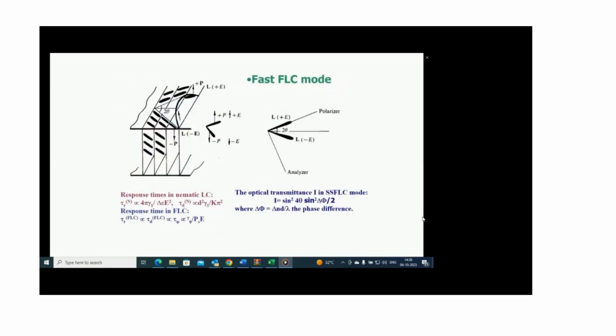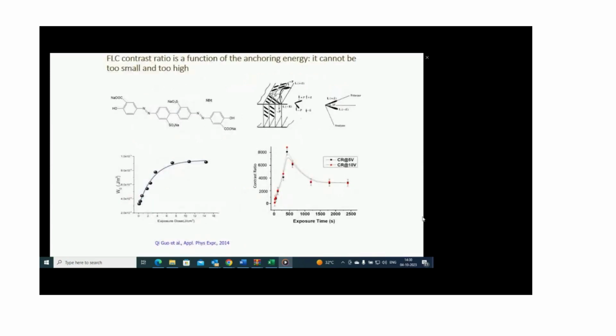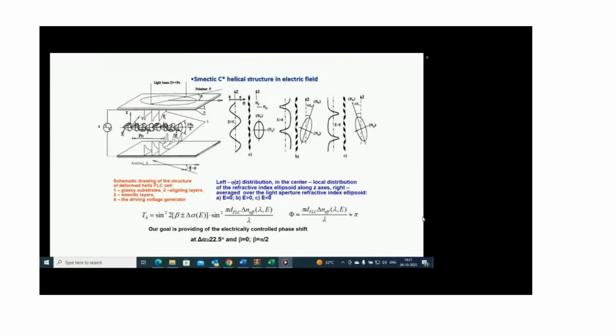liquid crystals. So roughly speaking, ferroelectric liquid crystal is a switchable phase retardation plate because it reacts with a linear electro-optical effect. So changing the direction of the electric field, you change the direction of phase. But it is very important for ferroelectric liquid crystal to have optimal anchoring energy. Anchoring energy cannot be too small, cannot be too high, because you align along zero, theta equal to zero, but switch between theta plus minus. So you cannot have low anchoring. So photoalignment is an excellent technology for liquid crystal.